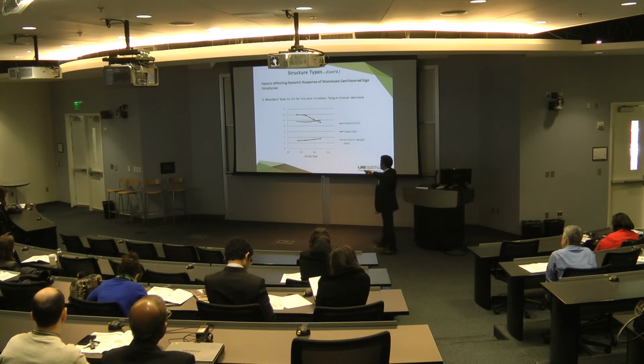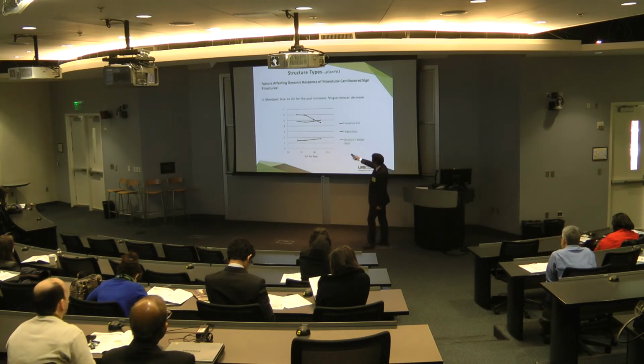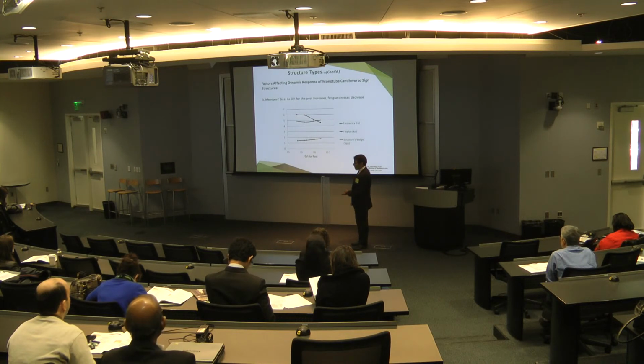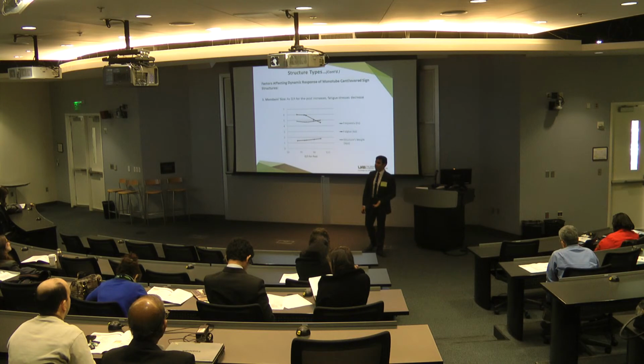As that D over T for the post was increasing, the frequency of the structure was increasing as well, and for that, fatigue stresses were reducing. And here, the middle line represents the weight of the structure. I found out that the structure's weight is not changing significantly, which means that if I increase it, it's okay. It's still economical and will be better for fatigue performance.